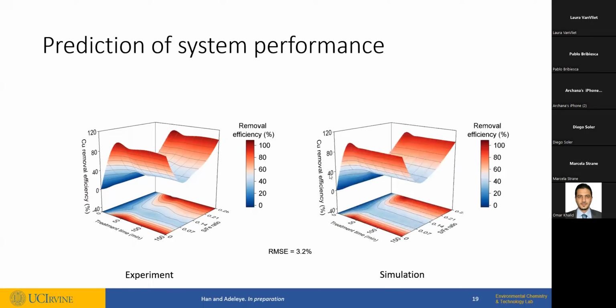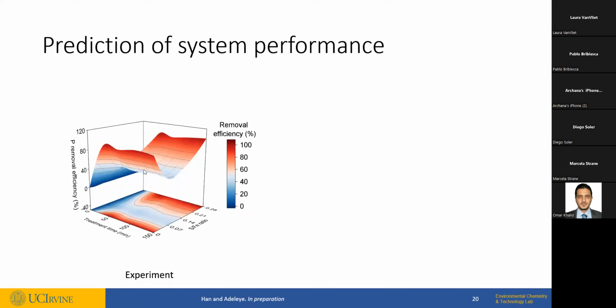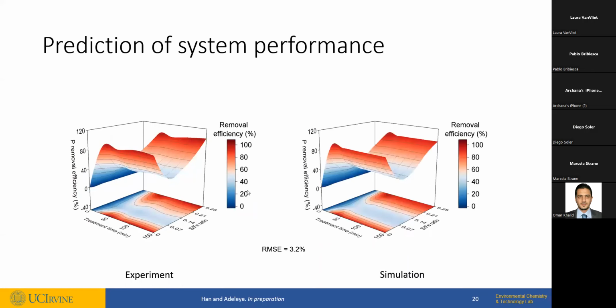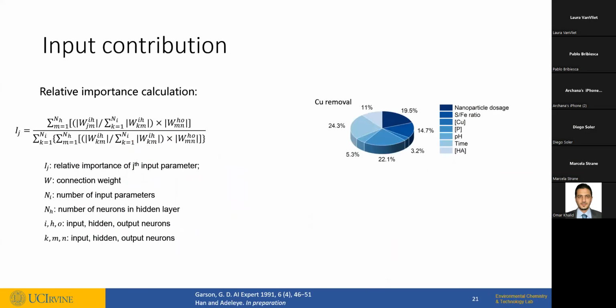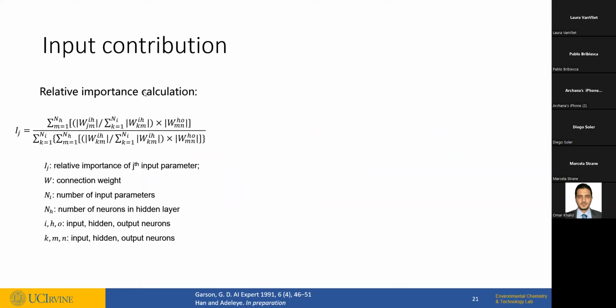And what was predicted by ANN is very similar. So you can see there is a lot of similarity between these two plots. The difference between them in terms of the root mean square error was about 3%. So there's just a 3% error chance by the function we came up with. So that was for copper. This is for phosphate. It's essentially the same thing. So we ended up having an ANN function that can effectively predict the performance of our nanoparticles based on different experimental conditions. And the last thing we did was to now ask the question,